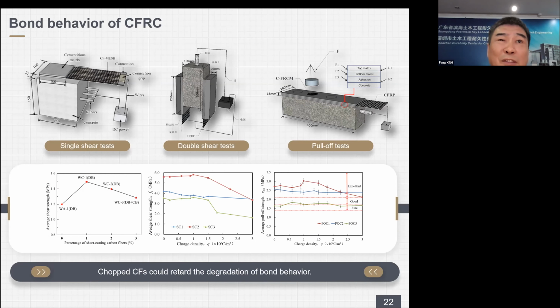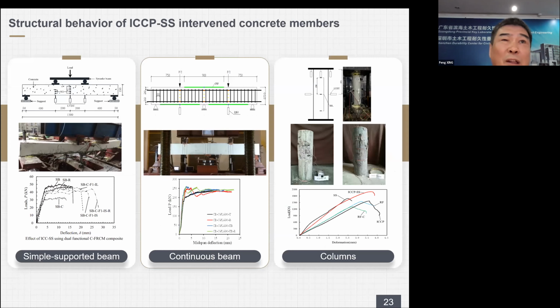Bond behavior was investigated with single shear, double shear, and pull-off tests. The specimens with designed CFRCM showed stable performance. And on that basis, a lot of work has been done on ICCP-SS member behavior, especially in static and fatigue loading conditions. It indicates that by adopting a reduction factor of CF, the current design methods of CFRCM strengthening concrete structures are generally conservative.